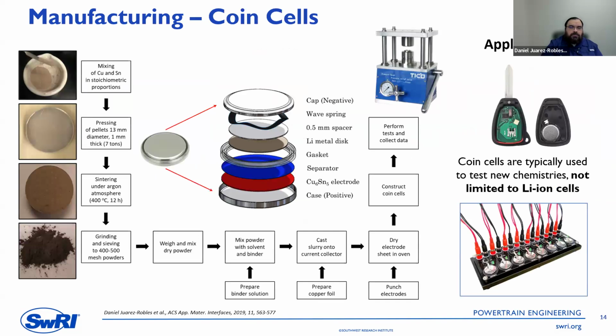Now, how do we manufacture some of these cells? When you talk about coin cells, the way that you prepare them is quite simple. You have all the parts, you can get them in the appropriate store, and the only thing that you change in this type of cell is the anode and cathode. In this case, we were using lithium metal as anode, and we were using a different material, copper tin, as cathode. You can have a conventional cell with graphite as anode, graphite here, and LFP here, and then you can test it.